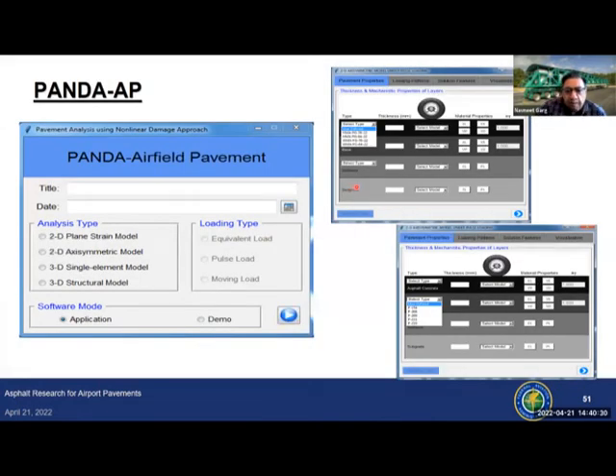These are some screenshots from Panda. So an asphalt layer can be modeled as an elastic layer, viscoplastic, or viscoelastic. The models for the asphalt layers have been pretty much finalized. We ended up spending much more time on the unbound aggregate materials because we wanted to capture the stress sensitivity of these materials and also be able to predict some kind of permanent deformation.